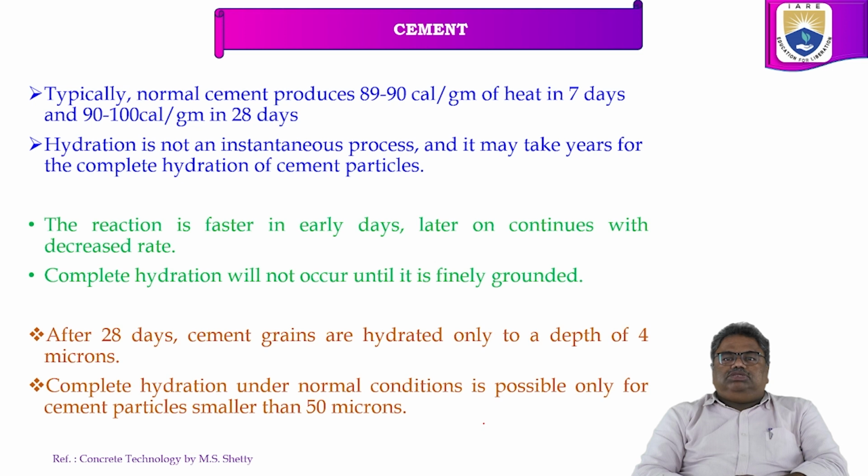If particles are more than 50 microns, it is very difficult to complete the hydration process under normal conditions.